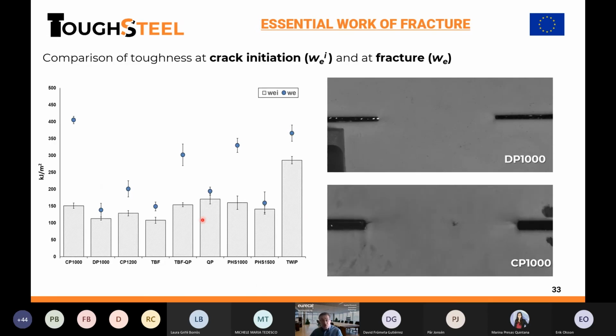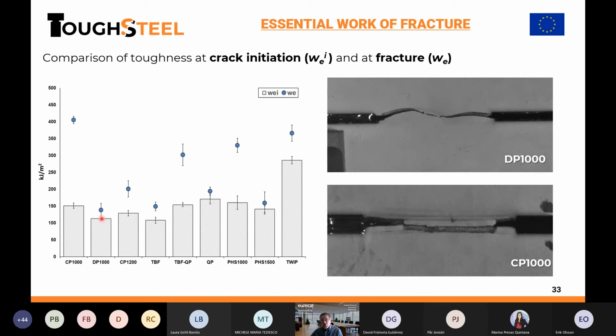But these are some results from different materials: complex phase, third generation steels, conventional partition, press hardened or TWIP high manganese steels. These are the values of initiation and the values of the final fracture. You can see that, depending on the steel, there is a difference between the initiation and the propagation. For instance, dual phase steels have a close distance between the initiation and the propagation.